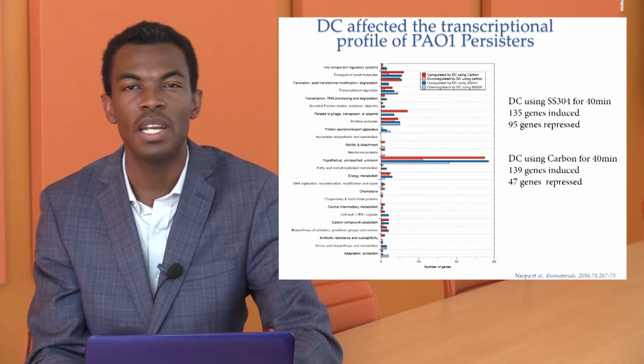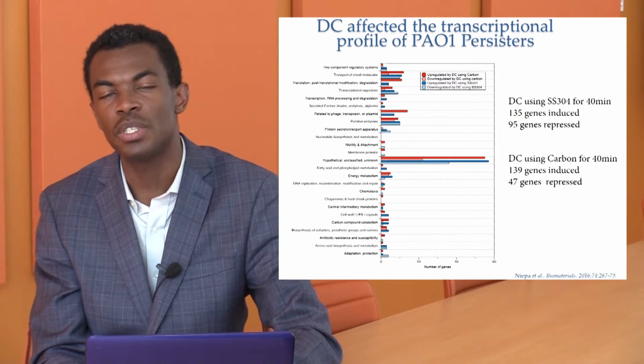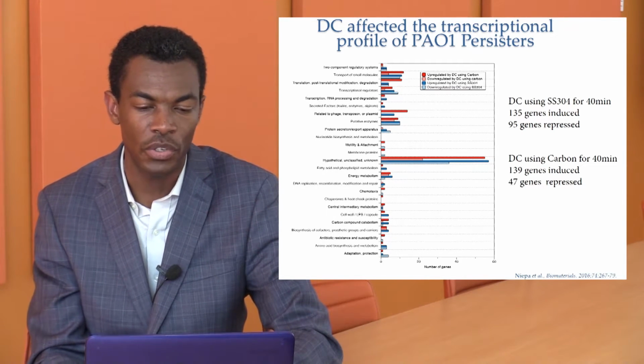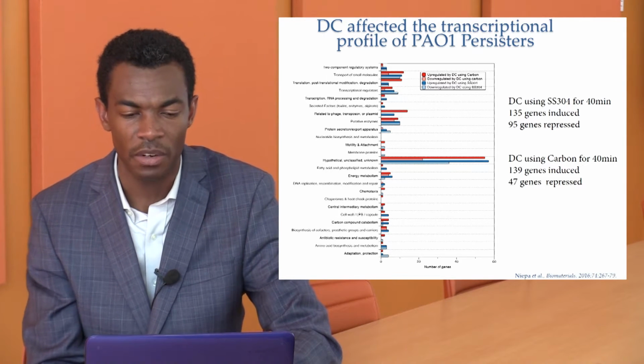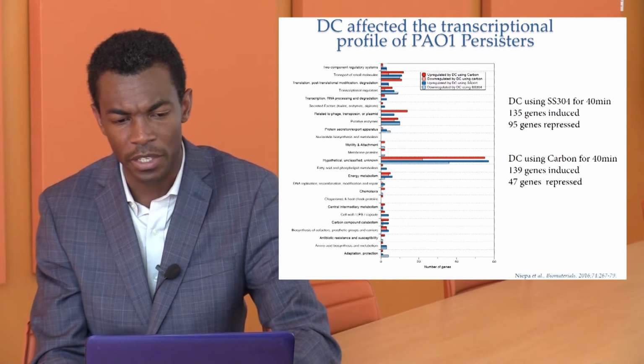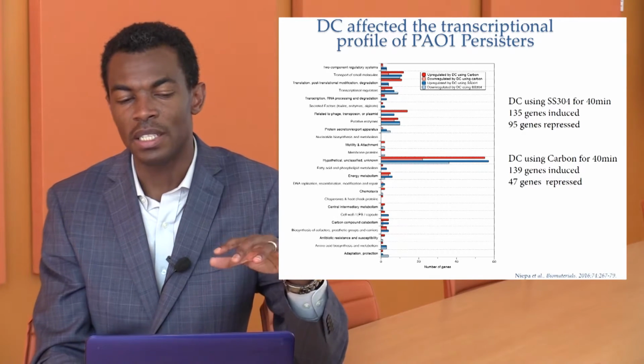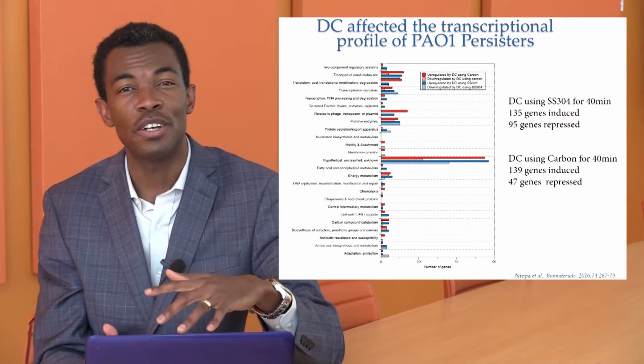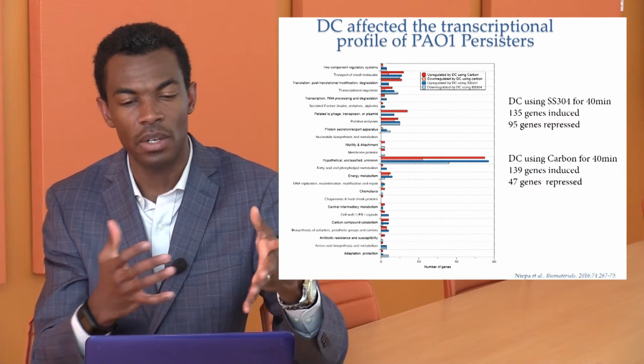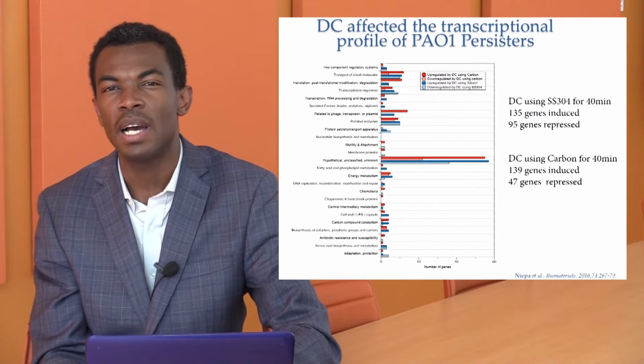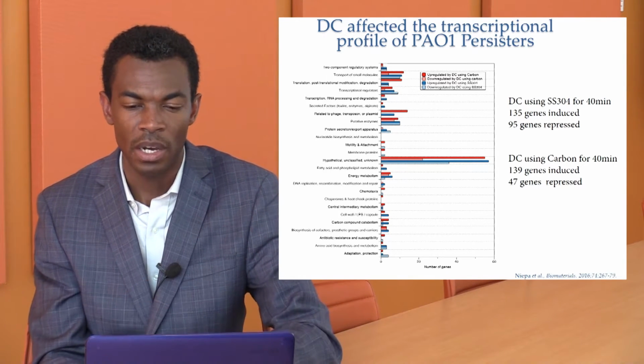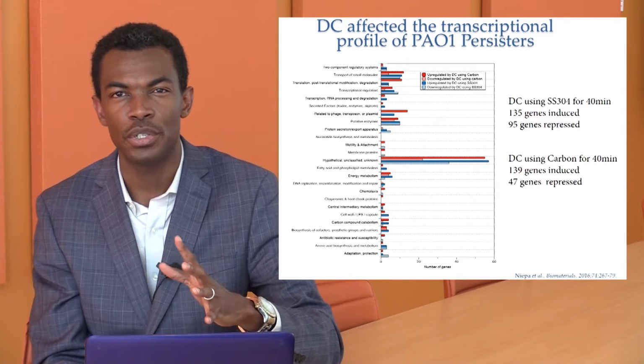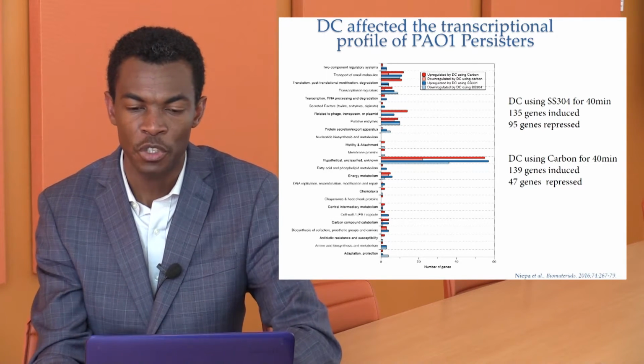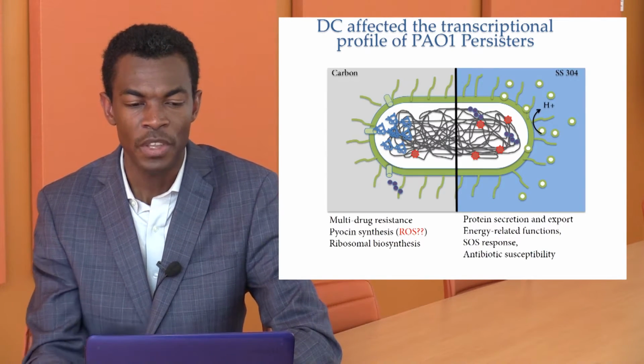But for carbon electrode especially, this is where we see most of the genes involved, 139 genes induced and 47 genes that are repressed. So that's a bunch of genes that were screened out of 5,000 genes, and depending on the data that we got, we saw that many of them have a certain signature that was representative of the treatment method.